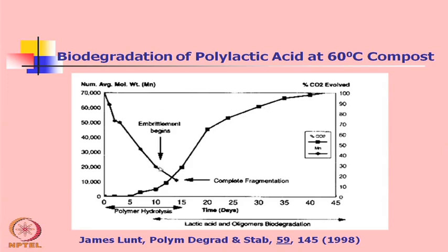Within 10 days, embrittlement of the polymer to fragmentation starts, and ultimately after 15 days, polylactic acid was completely fragmented at 60 degrees Celsius in compost condition.